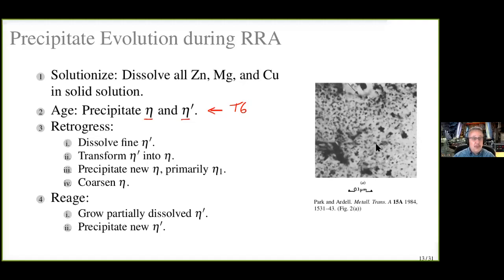So this retrogression and reaging not only gives us a very good strength as a result, we get better stress corrosion cracking behavior potentially. And now we're going to use this retrogression step right here to also make a part. Okay, but let's predict what times and temperatures we need for that.